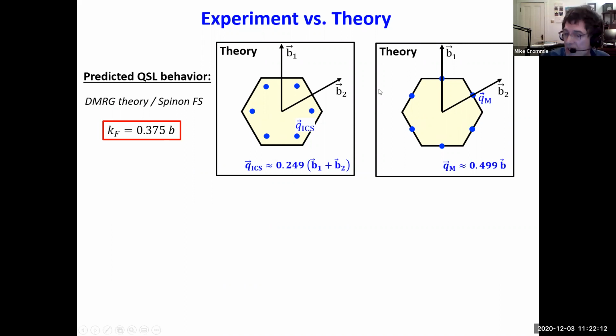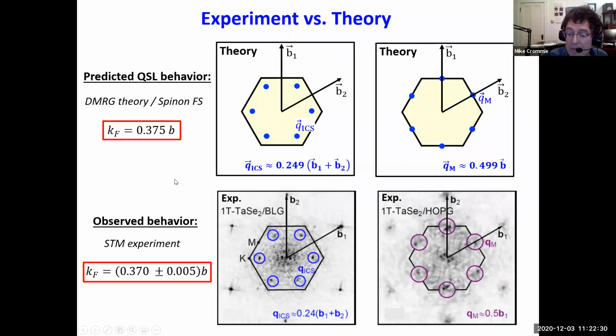And here I show the predictions. These are the predictions that you get from basically starting from the DMRG, the density matrix renormalization group theory. You end up with predictions that you should see spinon density waves at precisely these wave vectors that I'm showing you here, QICS and QM. Now I will show you what we see experimentally. These are the experimental density waves that we see. And as you can see, just by comparing them, the match is almost perfect. It's a really good match.